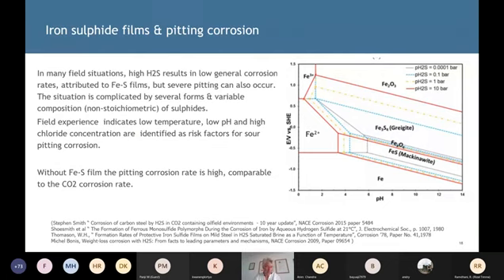This is a Pourbaix diagram for the iron sulfide system, and just to say that there are many forms of iron sulfide and they are non-stoichiometric. That means they're not perfect ratios of iron and sulfur, and they're not terrifically stable molecules. You get shifts between them, and their stability varies with pH as well, and temperature is a factor, and also chloride content is a factor. Many people have studied this, particularly ExxonMobil have a number of key presentations and papers on it, and Total as well.